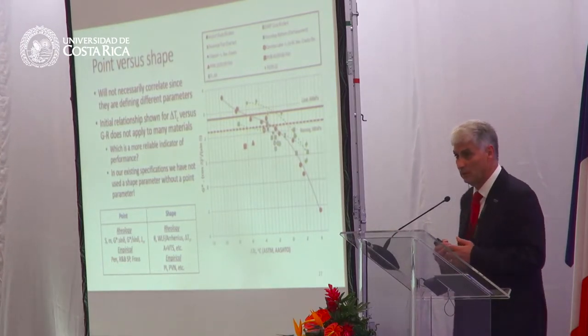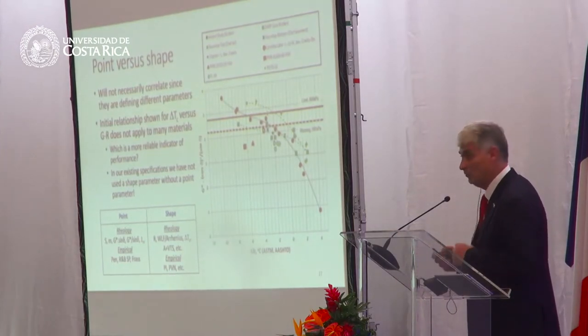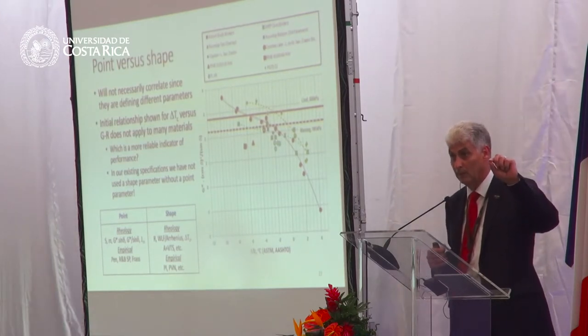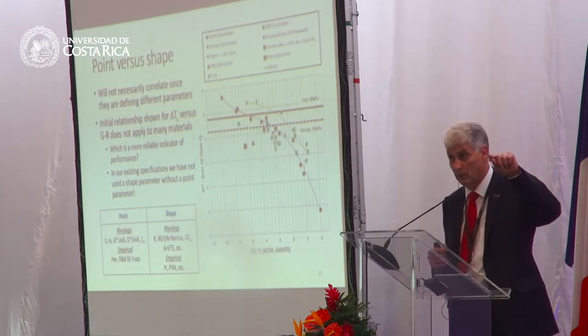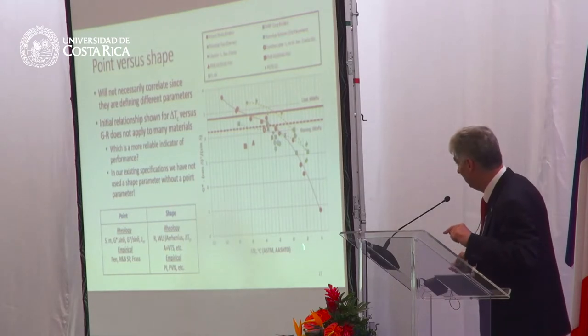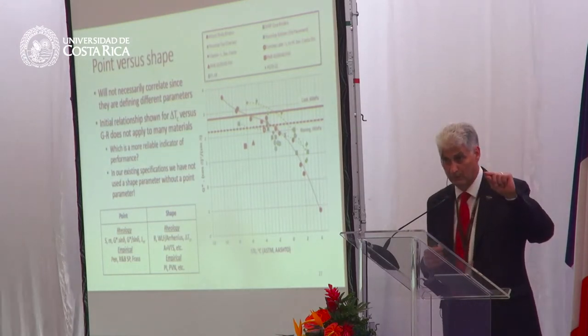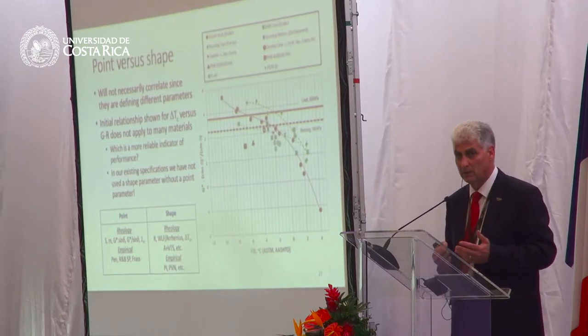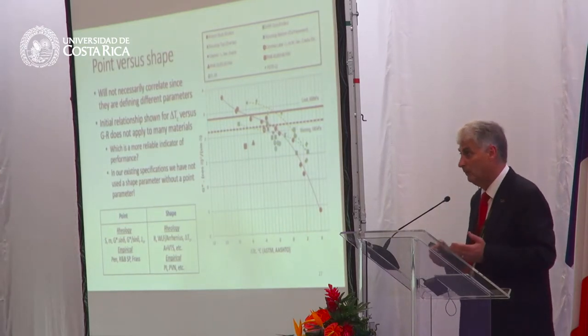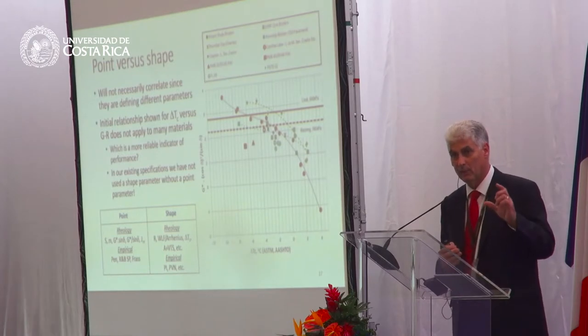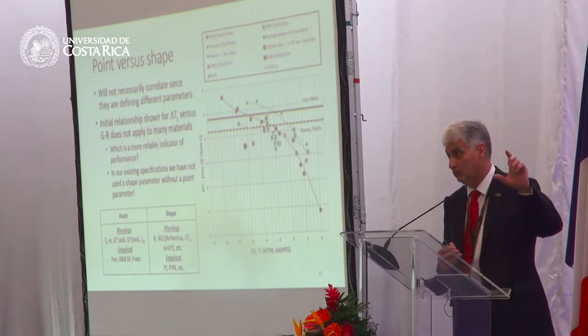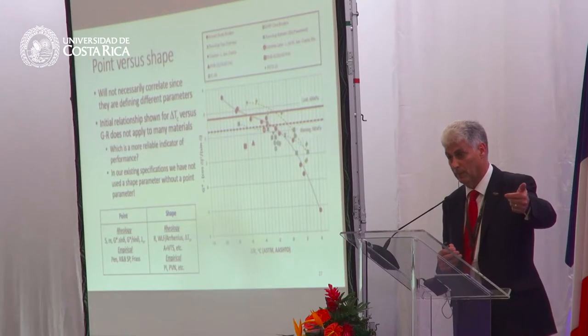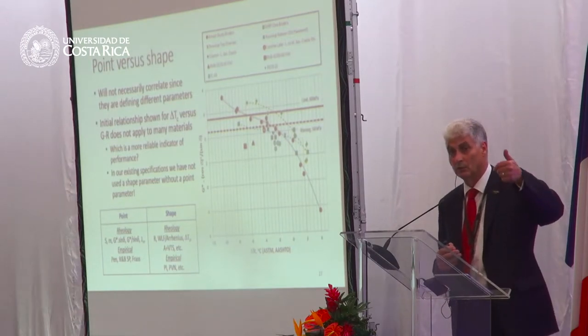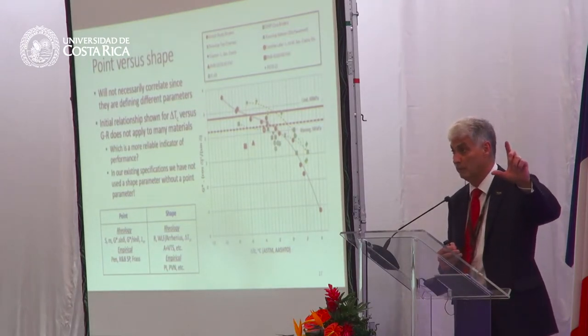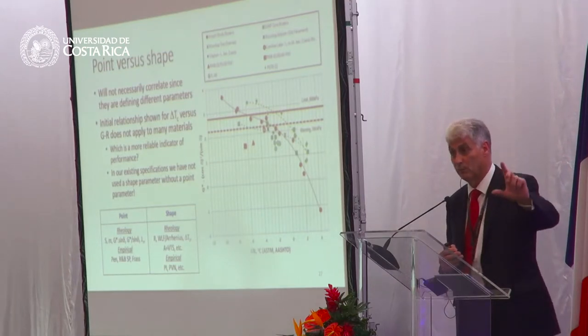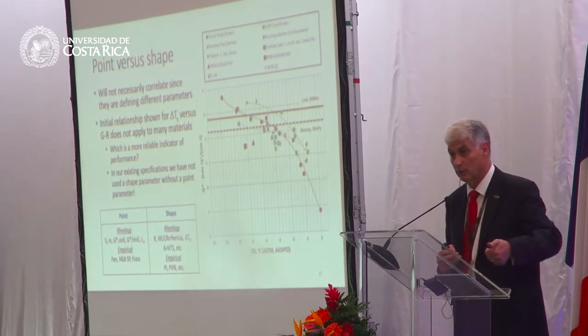And really this is the concept that this parameter here is measuring a point property. So it's measuring a point at a single loading time and a single frequency. This parameter here is measuring a slope parameter. If we think about how our binder specifications have traditionally been put together over the years, we either have in our specification 2 point parameters, or a point and a slope parameter. So 2 point parameters would be a pen and a softening point. A point and a slope parameter would be a pen and a penetration index.